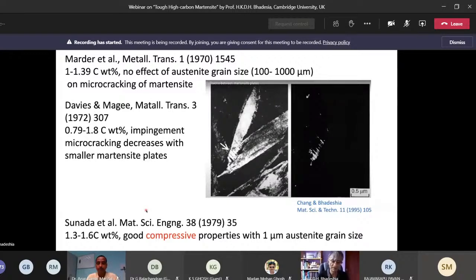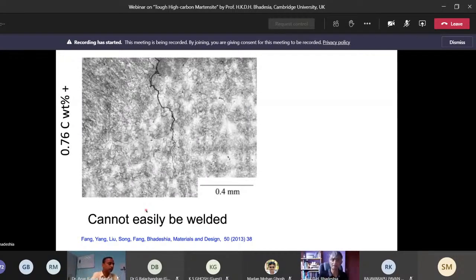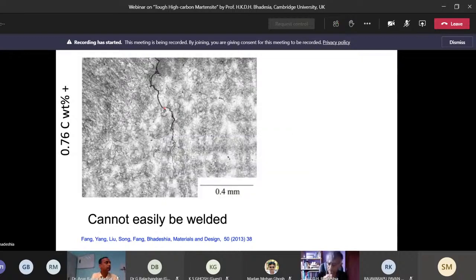And the problem with welding is that you put in a local heat source at the junction where you want to make the weld, and that will heat the adjacent steel. And in the heat affected zone, you will end up with quite coarse austenite grains, and then you will get cracking in the heat affected zone. So here is a welded region of a high carbon steel. This is 0.8 weight% carbon. And you can see here that you've got cracks going sometimes between the austenite grain boundaries. And the scale here is quite coarse. It's 0.4 millimeters or 400 micrometers. So these austenite grains are of the order of 70, 80 micrometers in size. And that grain growth has been caused by the heat input from the welding.